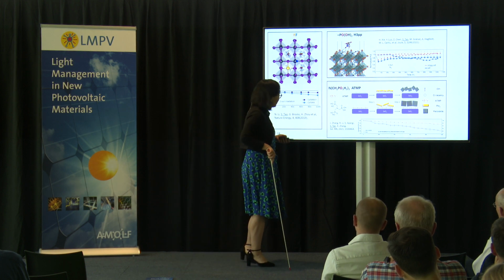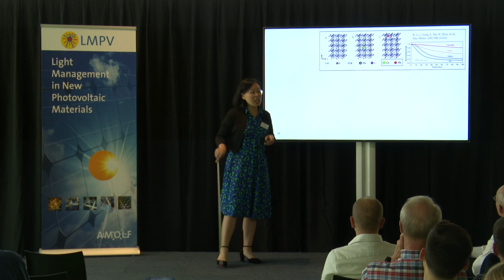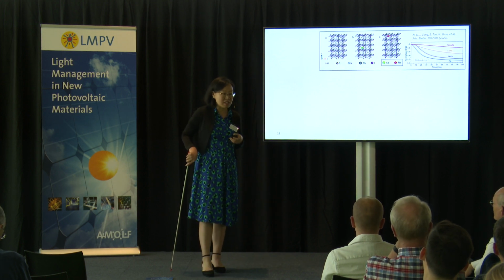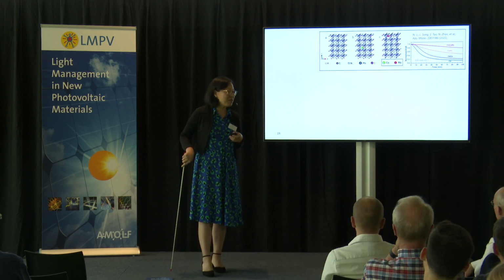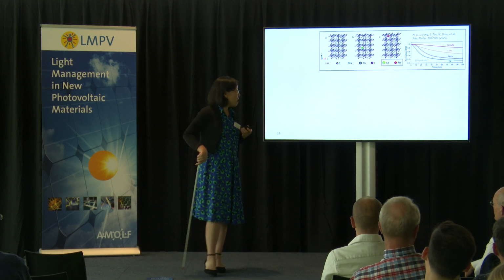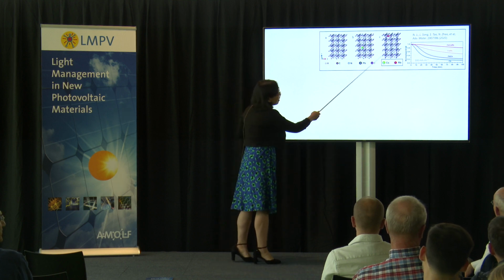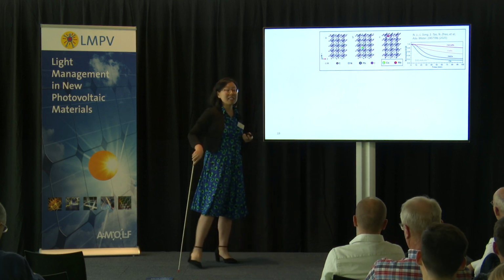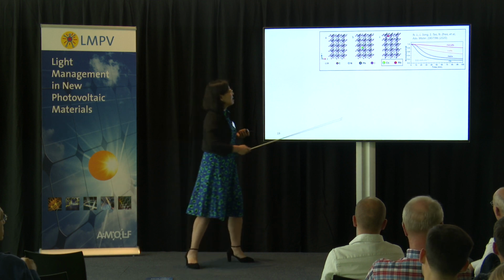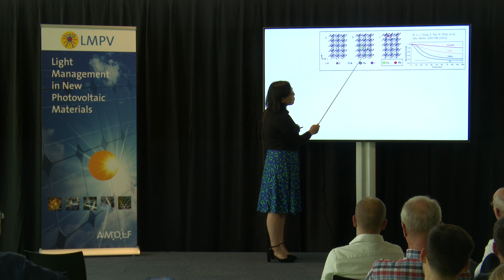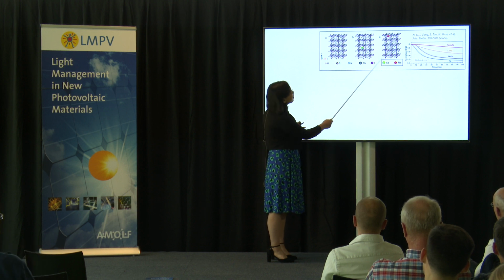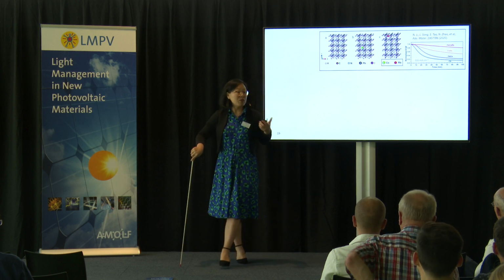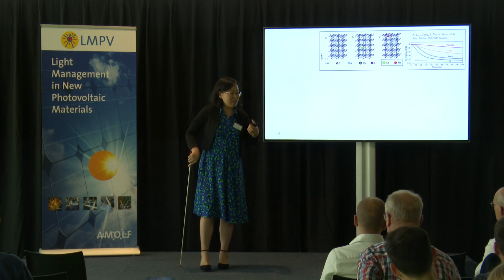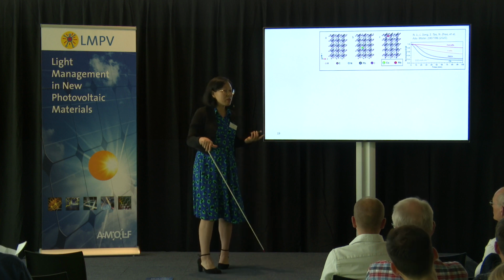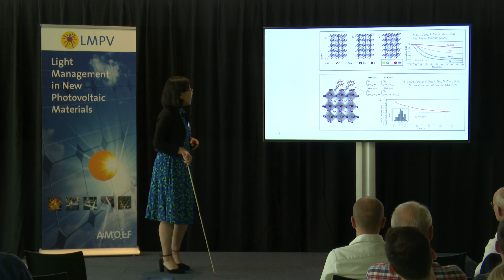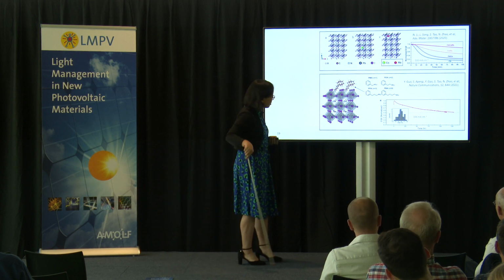The similar thing happens in LED, but there the electrical bias, the electrical stimulation, is the worst enemy for us. That means we have to immobilize the mobile ions. We do a similar kind of strategy. This time we put in small inorganic cations. These cations are very interesting. Cesium is just big enough to go to the bulk. Rubidium is a little smaller. It goes a little bit to the grain boundary. If we put a little bit of both in there, together they immobilize the film everywhere. The same story, a bit like the solar cells here.